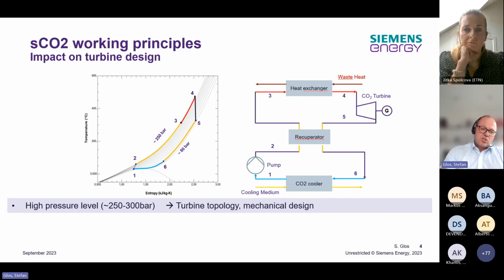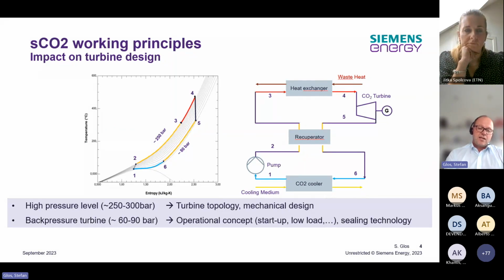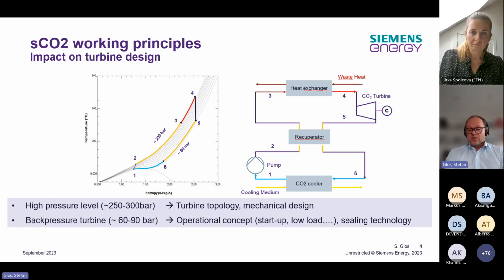And the second challenge comes from the fact that in sCO2 cycles we always have a back pressure turbine. That means the lowest pressure level in the system is in the area of 60 to 90 bars. And that implies specific requirements on the operational concept. That means how to start up the system. What about low load conditions or no load conditions? Have we thought about windage? And furthermore, the sealing technology, which was already mentioned in the first Slido.